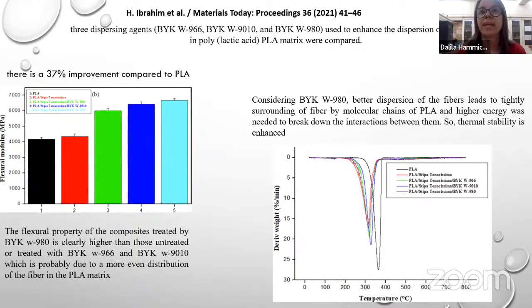It is also worth underlining that the degradation rate of the composite, according to thermogravimetric analysis, was considerably reduced, which suggests that the fiber retards the degradation of the matrix, in particular after treatment. The improvement of thermal stability of composite materials is attributed to the better dispersion of fiber and the formation of interaction between matrix and fibers instead of between fibers and fibers, which hindered the thermal degradation process of the composite. Here, I would like to say that the better dispersion after using the dispersing agent can improve the thermal behavior of the composite.